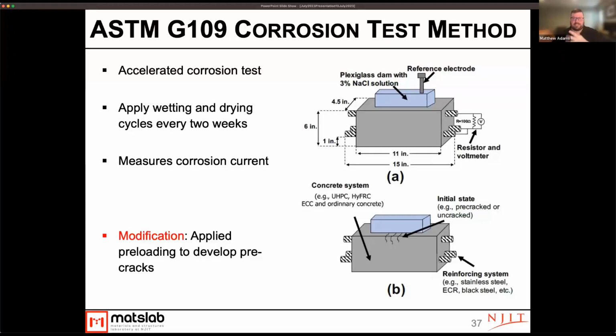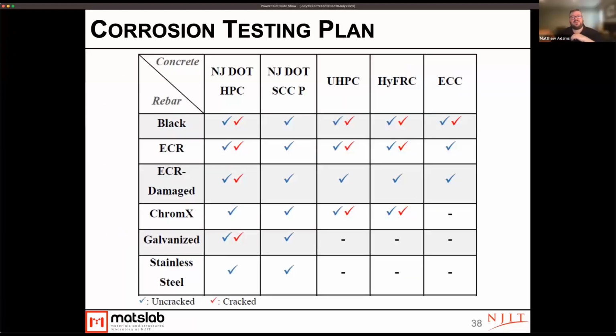However, with these ductile systems, and even with the normal concrete, you often don't see any damage, and you'll see from our results, in a year, even 2 years or 3 years time. And so to try to accelerate that and really show some more likely field situations where you do have some initial pre-cracking, either from loading or shrinkage of some sort, we looked at a modified version where we pre-cracked the systems. So we also looked at this across all 5 of our concrete mixtures, and then across our different rebar types, including some of the damaged epoxy coated rebar. And all of our systems we did in an uncracked state, and some of them we did in a cracked state as well, to sort of examine that role of cracking.